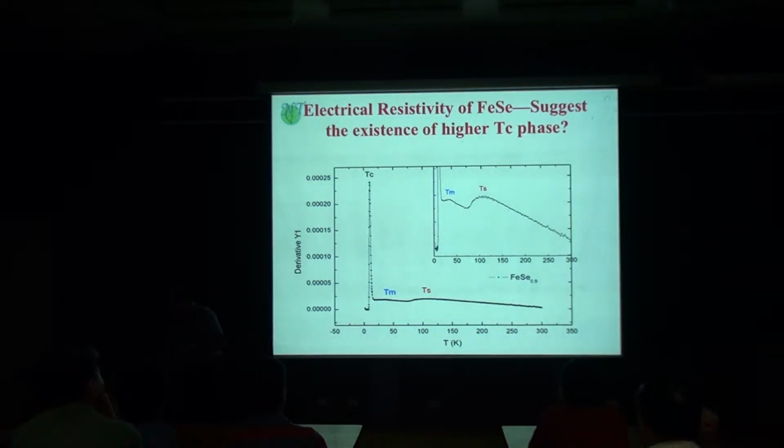What is here? We see, every time, something around 40 Kelvin. And immediately that lets us associate it with the pressure effect, right, which is 40 K. Which means that maybe this system already has this 40 Kelvin phase, although it's only a very small amount. So we'll be asking whether such a high TC phase exists. This is one question.